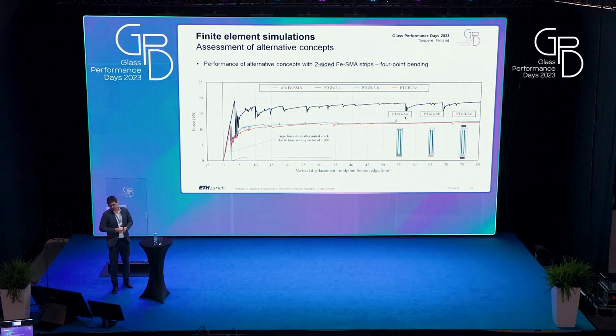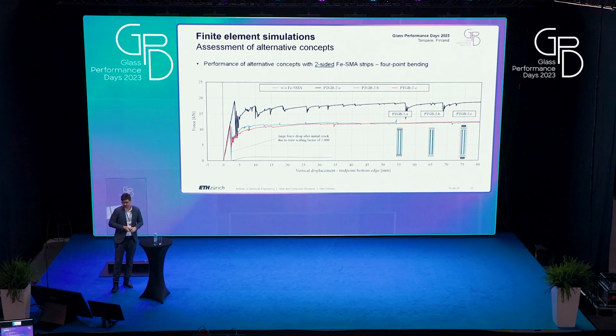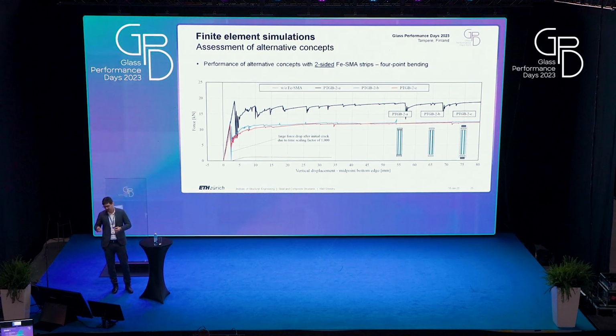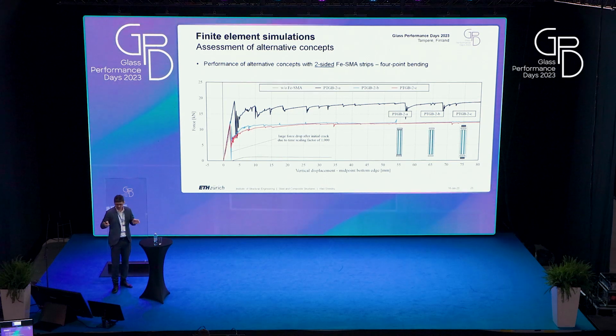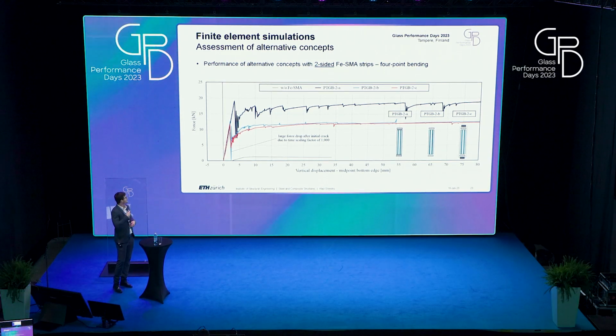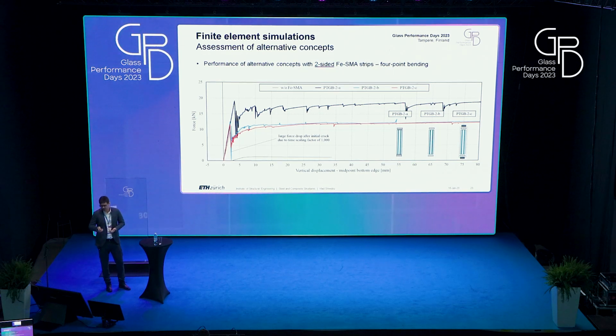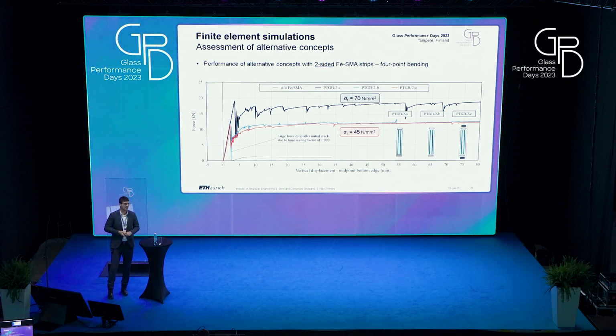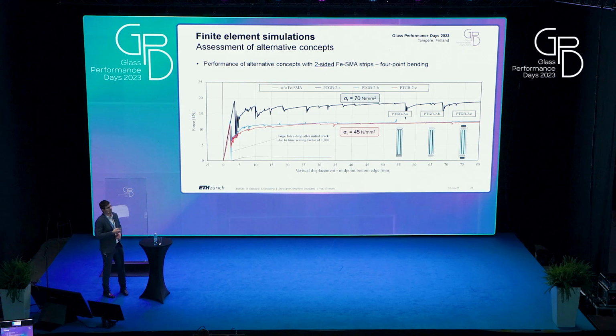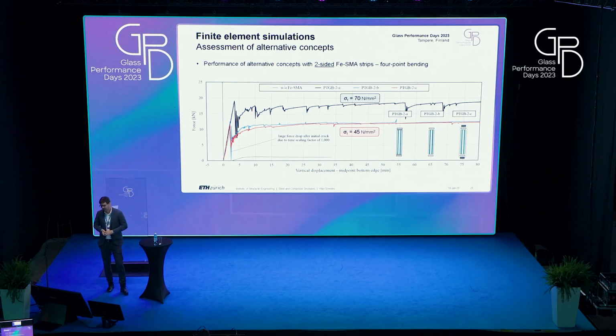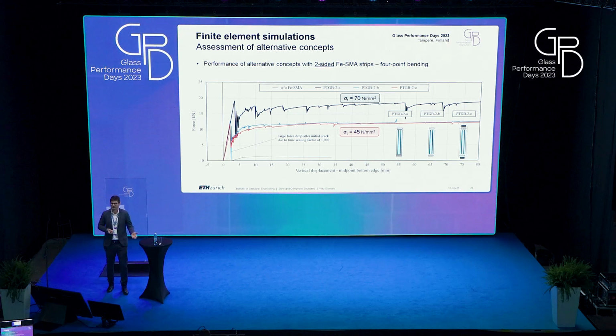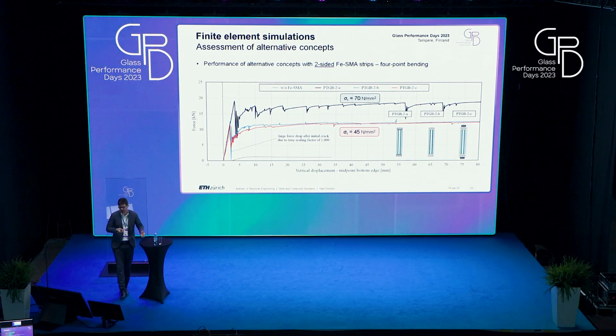If we look at the force displacement curves for these different types of beams, we can directly see that the ones with adhesive bonding along the whole length of the edges, the black curve, reach higher forces. But this is especially because of the assumed failure stress for the glass. For the black curve, we assumed this higher stress value based on the strains that we measured in the experiments. For the other type of beam, since we don't have adhesive in the middle part where the crack will occur, we expect that the failure stress will stay in the range of the characteristic strength of the annealed glass.